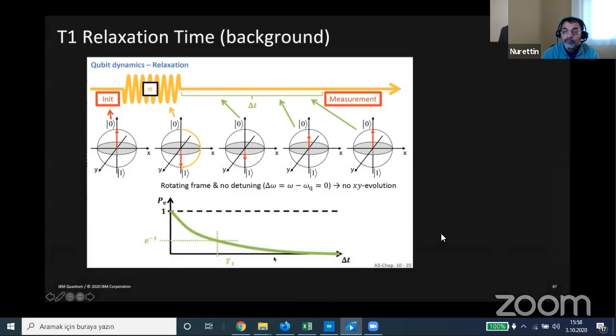And we fit this to an exponential. Actually, our data has a very good fit to the exponential. Chi-squared fit is very good. And the time at which the probability drops by 1 over e, we call the T1 time. So it's an exponential, e to the minus t over T1.